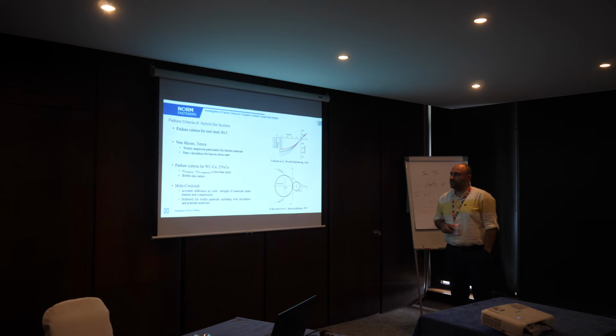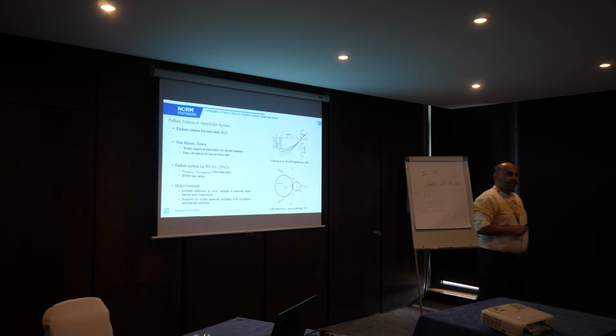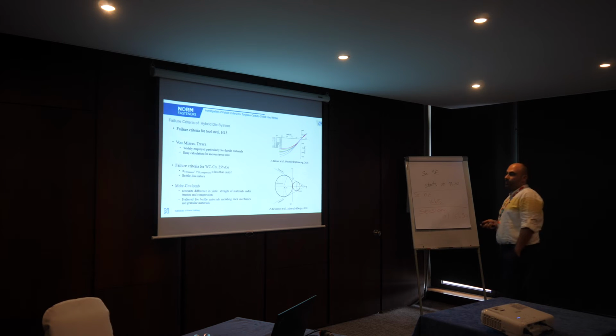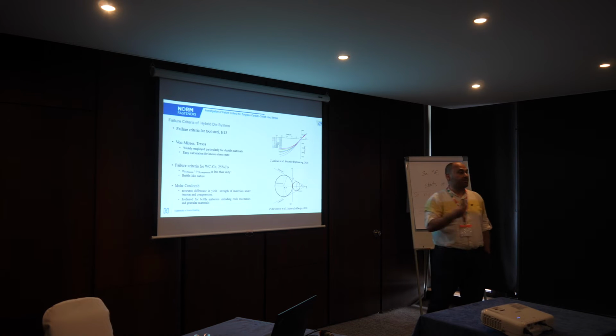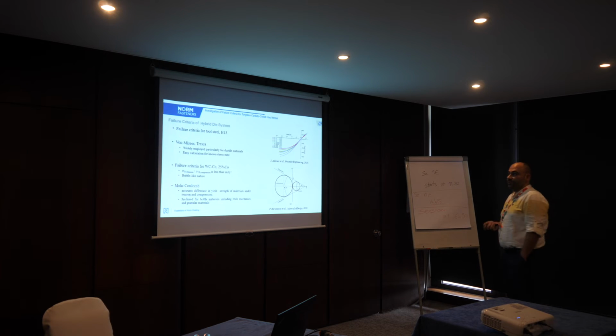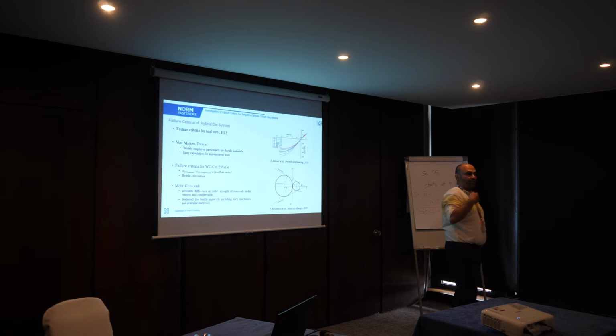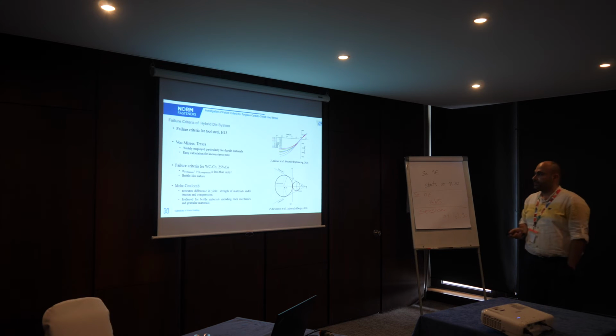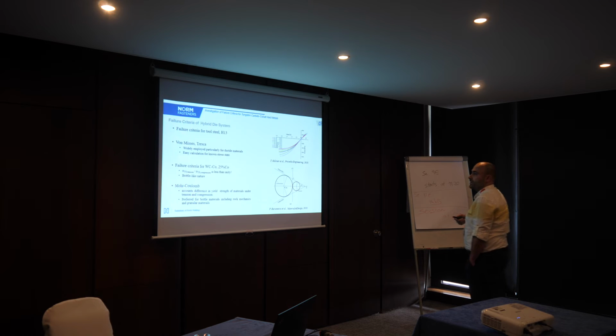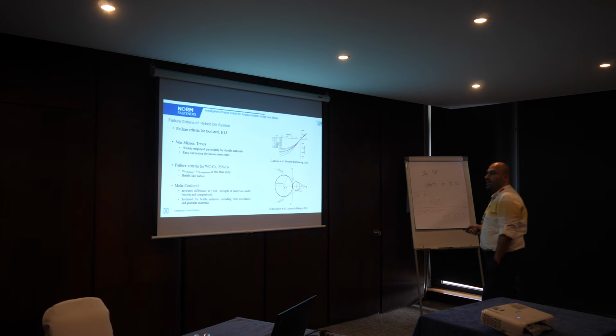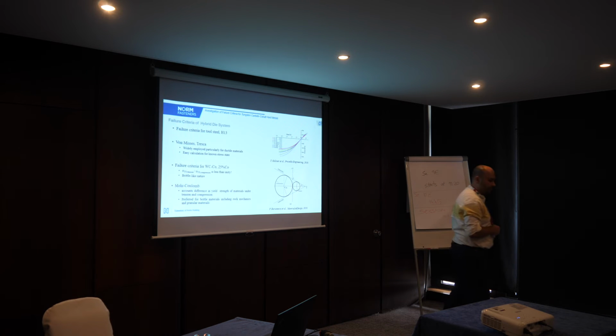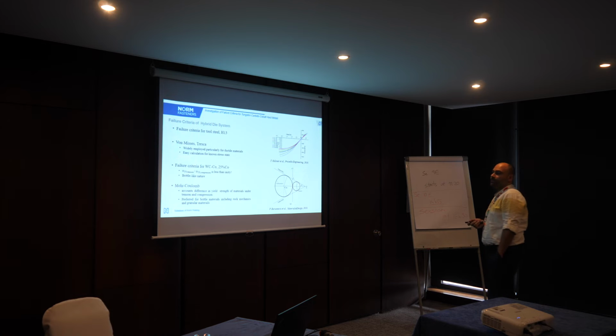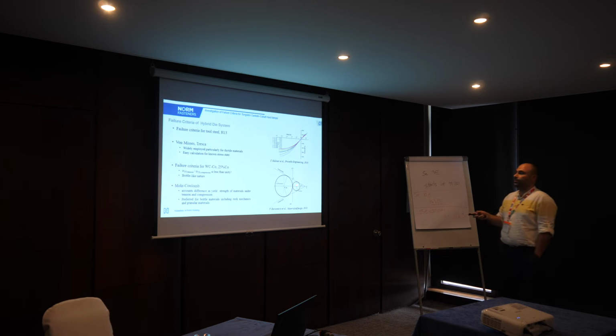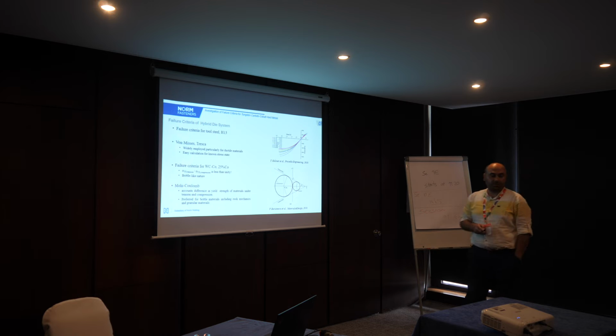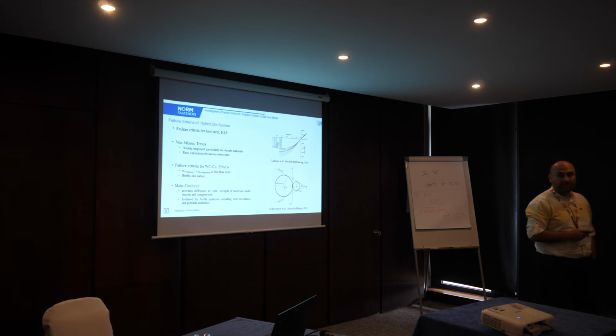So there is a significant difference between tension and compression, and von Mises and Tresca can't deal with this difference. And we know that tungsten carbide cobalts are of brittle-like nature. I'm saying brittle-like because pure tungsten carbide is a ceramic material, so it should be brittle, but with the addition of a significant amount of cobalt, we are introducing some ductility, and this is also required for cold forging dies. So while looking in the literature for which failure criteria we can apply for tungsten carbide cobalt, we came up with the Mohr-Coulomb failure criterion. This one takes into account the difference between tension and compression, and it's also preferred particularly in rock mechanics and granular materials where materials are brittle.